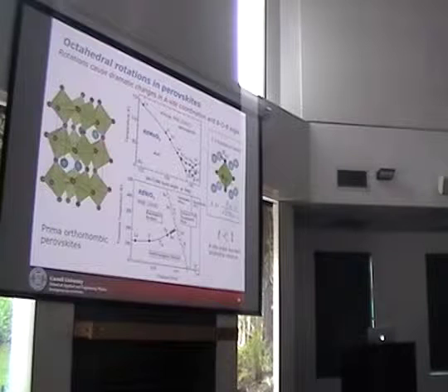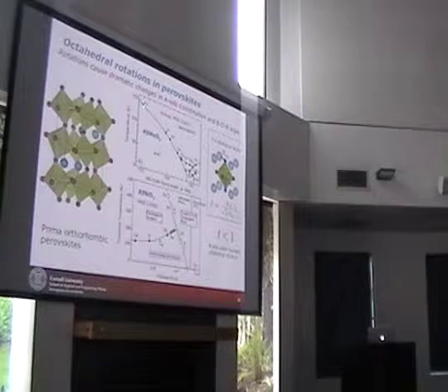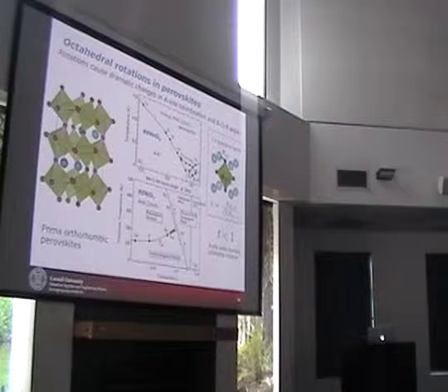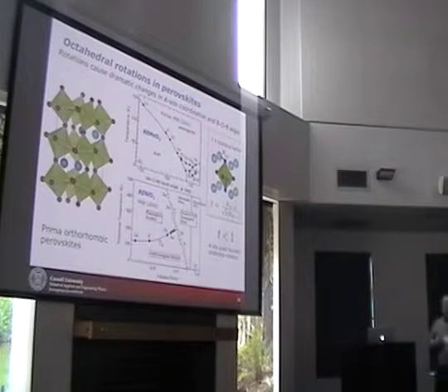Here I'm just showing you 2 phase diagrams of 2 examples. I could show you for just about every transition metal oxide a diagram like this. This is a rare earth manganite, this is a rare earth nickelate from the bottom. What you're seeing here is temperature versus some parameter, which I'll mention in just a bit. The dots refer to different compounds, from lanthanum all the way down to holmium in this case. These are all 3+ cations. Again, these are all 3+ cations. These are isovalent substitutions. We are not adding or taking away electrons, simply changing the size of the cation on the A site.